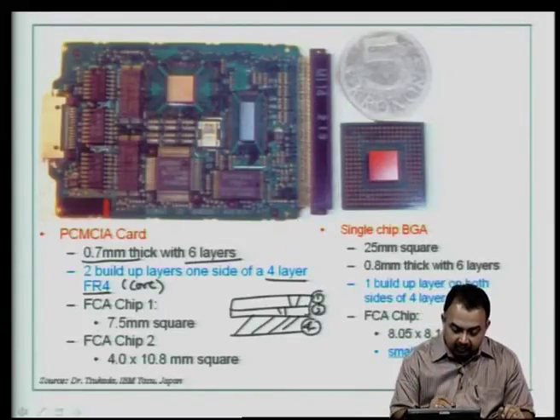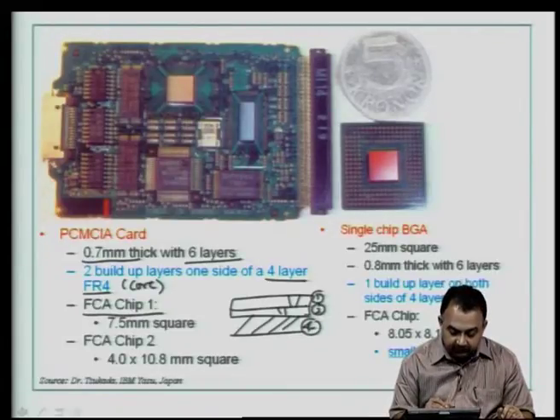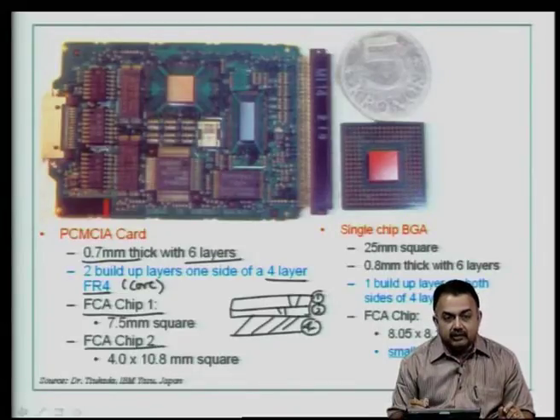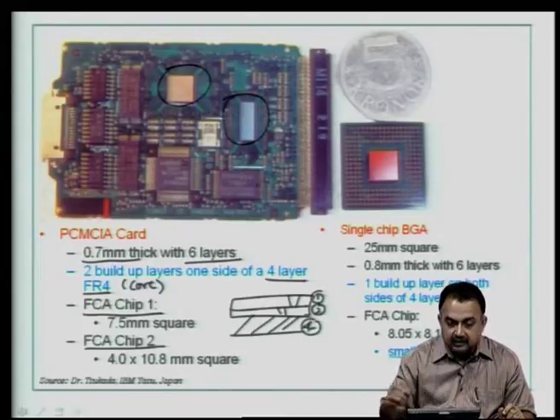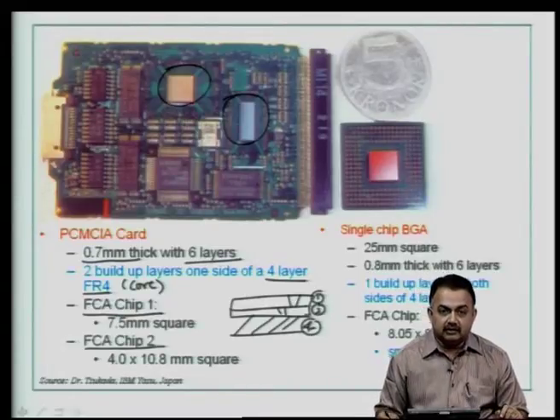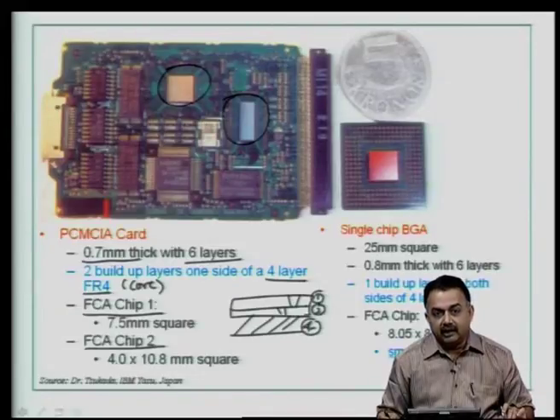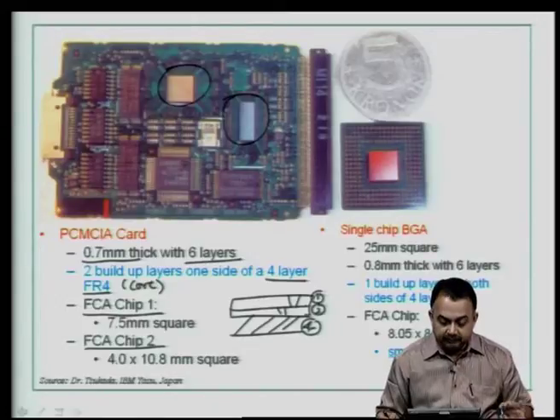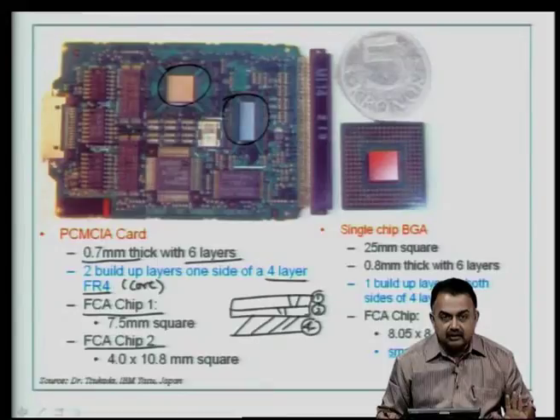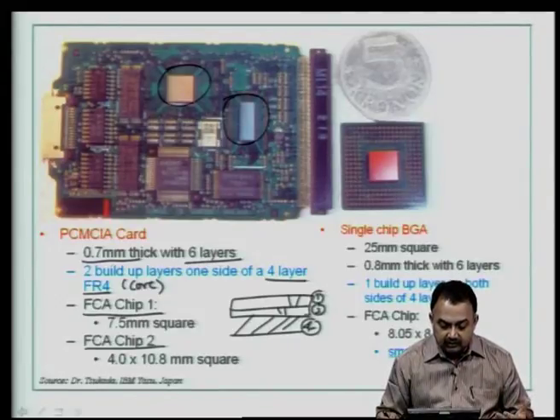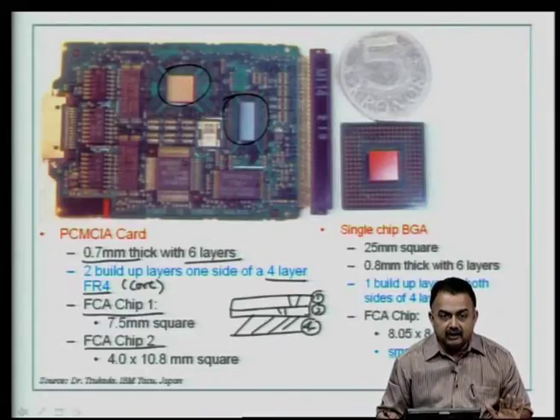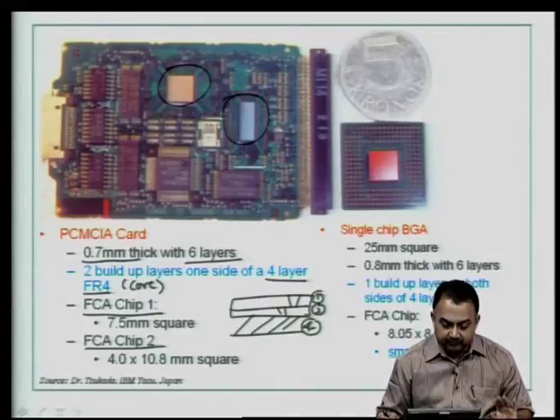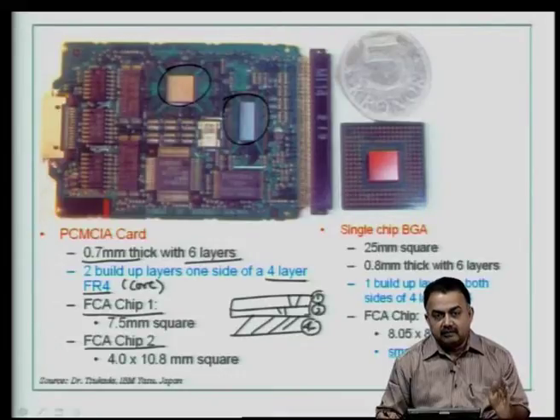So, these were provided with a lot of Microvia structures to interconnect to the core substrate. And you can see here it has accommodated flip chip, one which is 7.5 mm square, and the other is a flip chip 2 which is 4 by 10.8 mm square. So, these are the flip chip substrates that have been mounted. This is a classic example, an introduction from IBM about the usage of bare die directly onto the substrates. There is no packaging, it is a bare die flip chip methodology, and it is a reliable interconnect. In addition, you can see all the components are surface mount, including the resistors and capacitors. Absolutely, it has eliminated mechanical drilling except in the core structure, and no through hole components have been used. So, this is how the progression has taken place from conventional multilayer boards, where the limitations have been there for high performance because of the size.